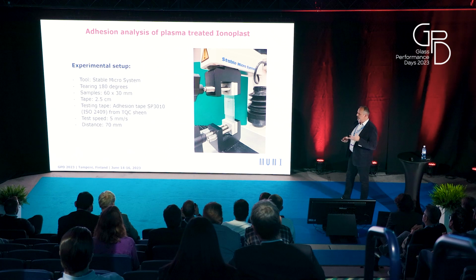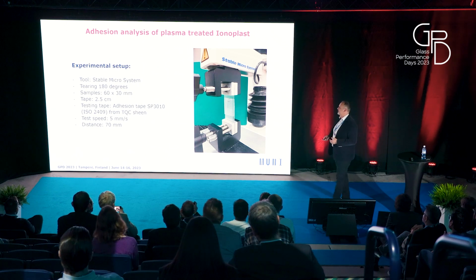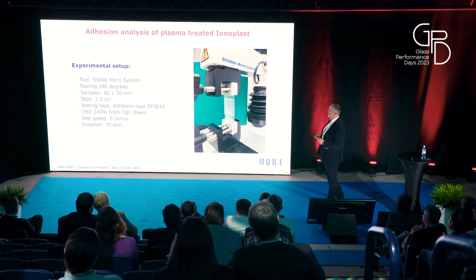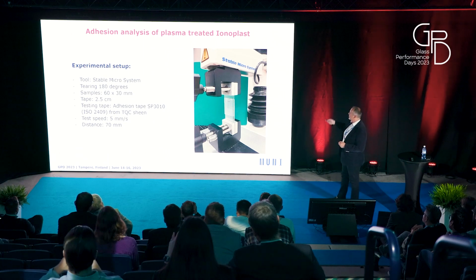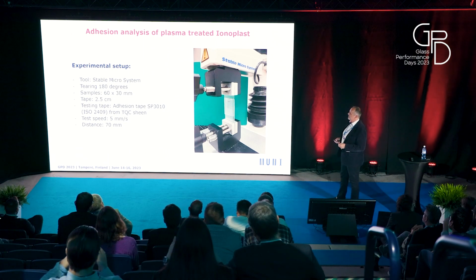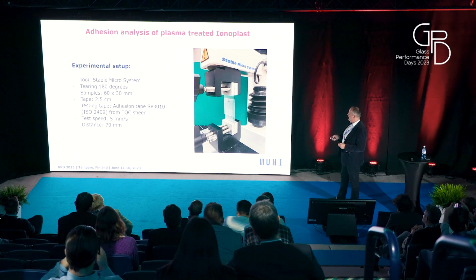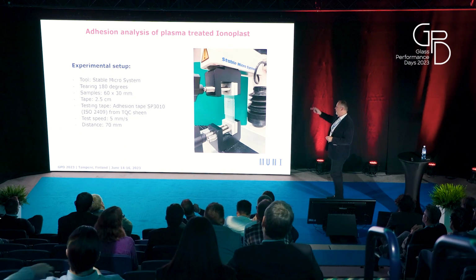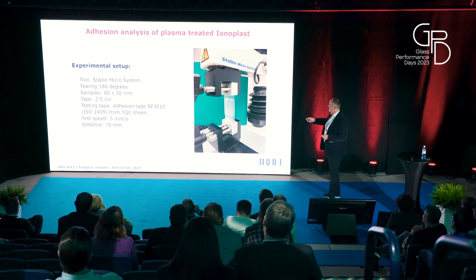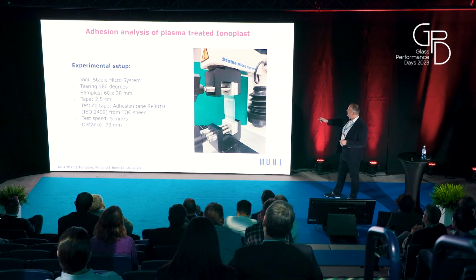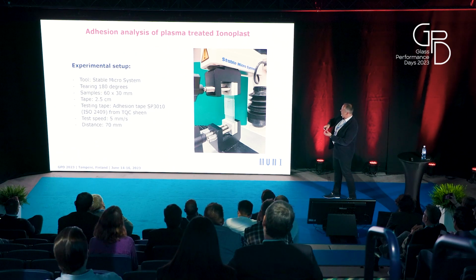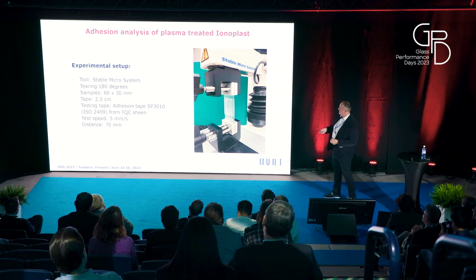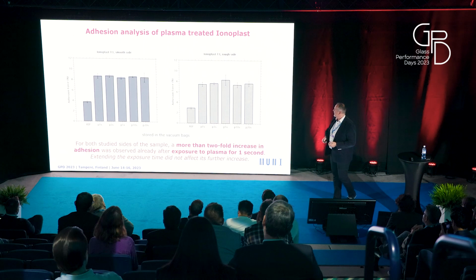Good wettability, lower contact angle, and higher surface energy are quite a good indicator of better adhesion. So we also investigated adhesion using the tape peel test method at an angle of 180 degrees using a testing tape. We were measuring the force which is necessary to remove the tape from the SentryGlas.